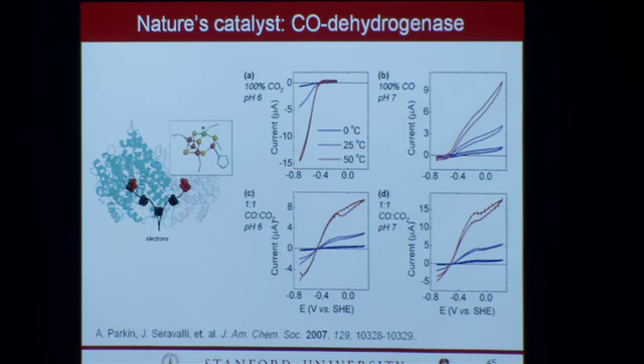And so really what we're after, again, is we're looking at mimics of enzymes to tackle this problem. And here's one particular enzyme, carbon monoxide dehydrogenase, which is a really interesting system that these researchers a few years back had supported onto an electrode, and were actually able to oxidize CO to CO2, and reduce CO2 to CO at the reversible potential. So these are very interesting catalysts, iron nickel sulfide catalysts.